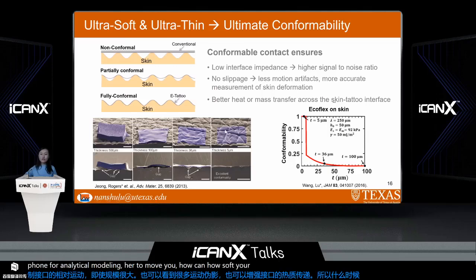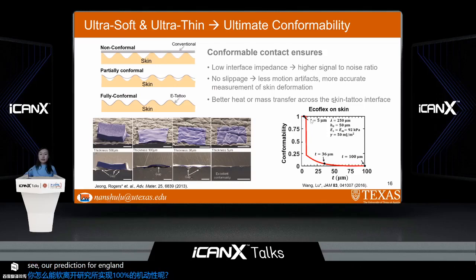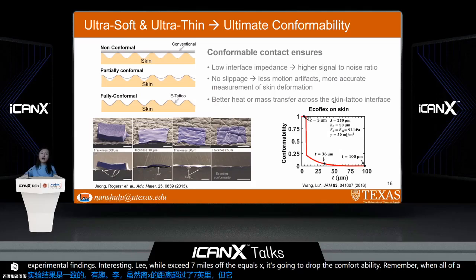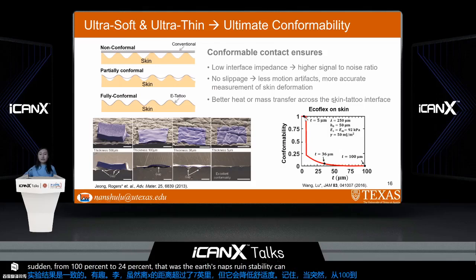As we can see, our prediction for EcoFlex on skin is that only when it's thinner than 7 micron, it is able to achieve 100% conformability, and that is fully consistent with the experimental findings. And interestingly, once we exceed 7 micron thickness of the EcoFlex, the conformability drops significantly all of a sudden from 100% to 24%. That is a snap-through instability in mechanics. And then at 36 micron thickness, almost no conformability. At 100 micron, forget about it.